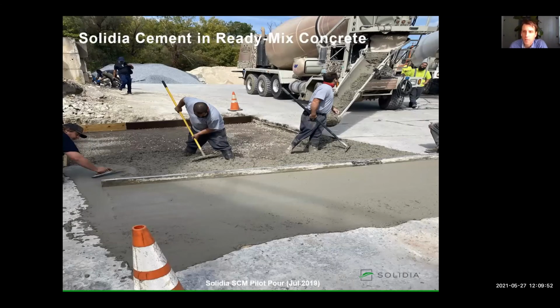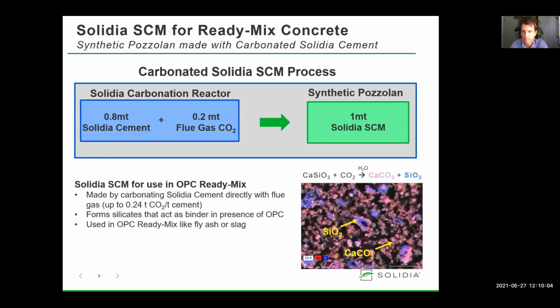In this section, I'll talk about how Solidia cement, which reacts with gas phase CO2 to cure, can be used in ready-mix applications in a way that doesn't require CO2 gas for curing during end use and at the final end use site. One way that Solidia cement can be used in ready-mix applications is by using it to make a synthetic pozzolan, we refer to this as Solidia SCM, that can be added to OPC-based concrete. Like fly ash or slag, Solidia SCM can be used to replace up to 50% of OPC in concrete and has been shown to improve concrete performance.